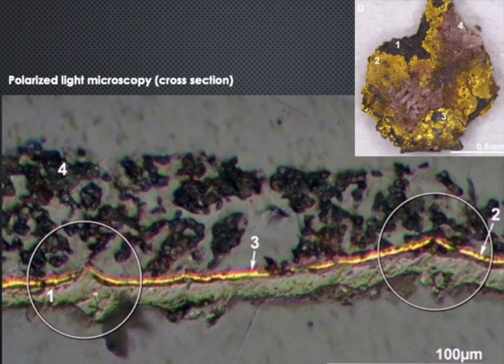The sequence of layers of our corroded gilded tin from inside to outside is as follows. Layer one is a grey-black metal foil. Layer two is a metallic yellow leaf. Layer three is a fine, shiny covering. And layer four is a purple-tinted whitish coat. Crater-shaped voids are created in the golden leaf, surely formed during its burnishing on the tin foil.